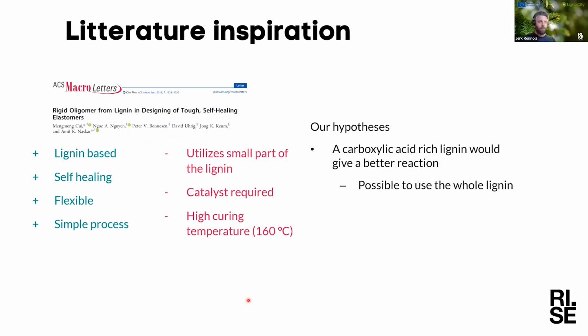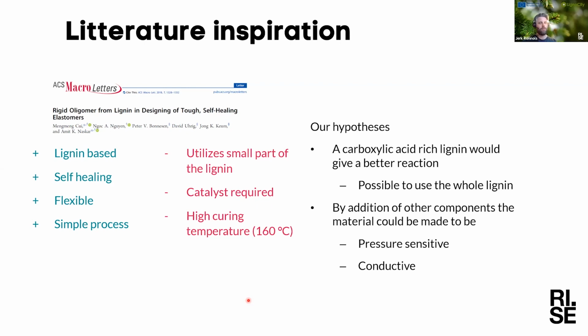So we hypothesized that carboxylic acid-rich lignin would give a better reaction based on what they had proposed, which would make it possible to use the whole lignin for making materials such like these. And also that it could be possible to add various components to the material to make it A, pressure sensitive, and B, conductive. So this is what we are investigating here.